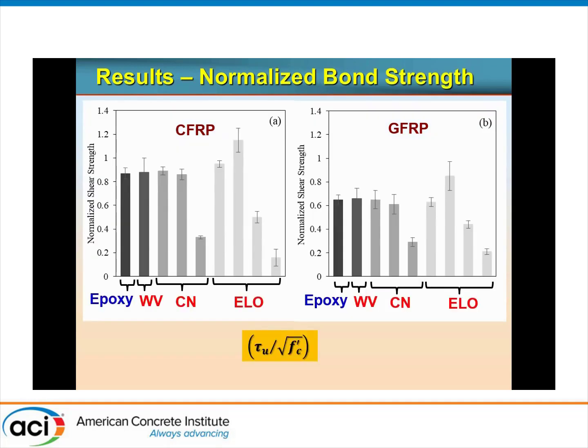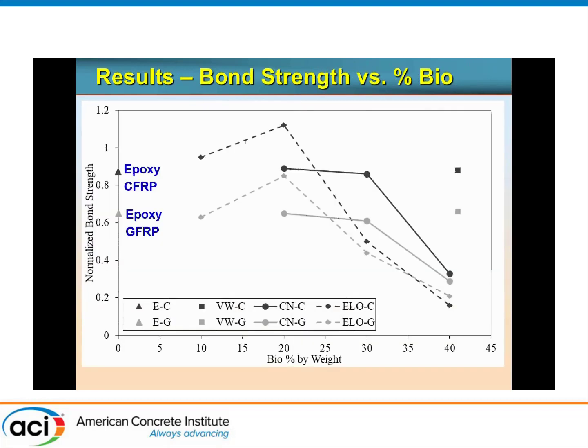But there were slight variations because there were a number of concrete batches, so there were slight variations in fc prime. So we thought we might normalize with respect to the changes in the concrete strengths. So we have the normalized bond strength, tau over the square root of fc prime. It changed slightly from the previous slide, just to be more accurate. This shows you again the normalized bond strength versus the percentage bio by weight in the resin. So that's the control epoxy carbon and glass for bond strength. This is the WV for carbon and glass. This is the CN, and that's the ELO, varying from 10, 20, 30, and 40, or 20, 30, and 40 for the CN resins.